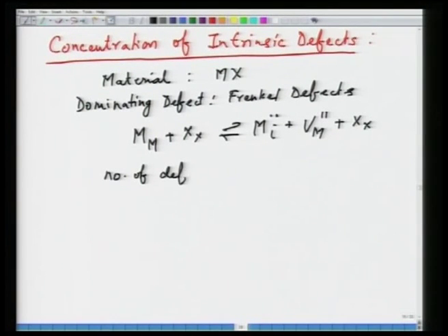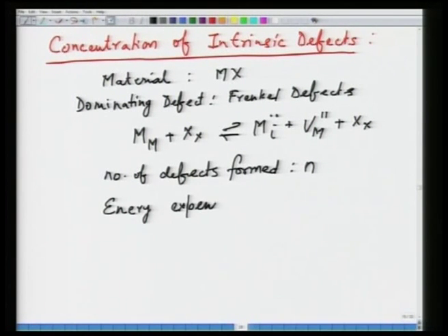So, let us say the number of defects that are formed are n, and the energy expense per defect, let us say, is delta GF. So, basically per defect pair, you can say, because here you are going to form a pair. So, the moment you form a metal interstitial, you have a metal vacancy.